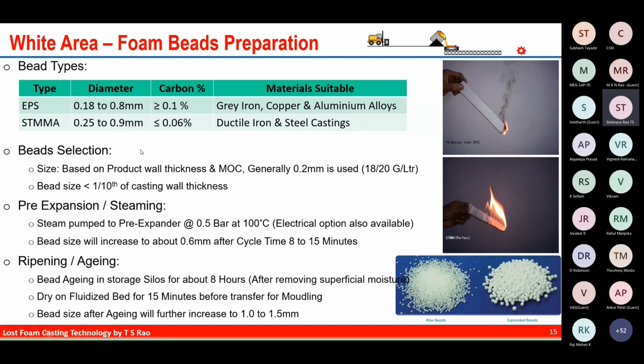And for the bead selection, normally the bead selection depends on the material of construction of the part. Generally 0.2 mm is used, which is like if you take a 1 liter jar, the beads weigh about 18 to 20 grams. The thumb rule is the bead size should be 1/10 of the casting wall thickness. If the wall thickness is 2 millimeter, then the bead size should be 1/10, it is 0.2 millimeter. So that is the thumb rule.